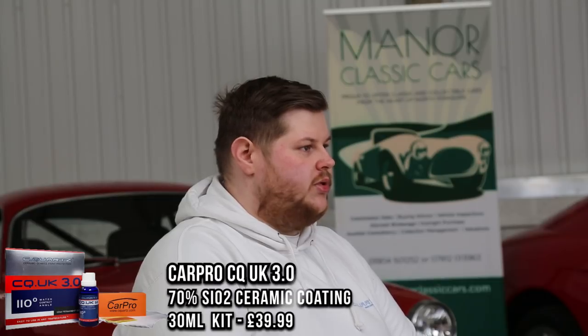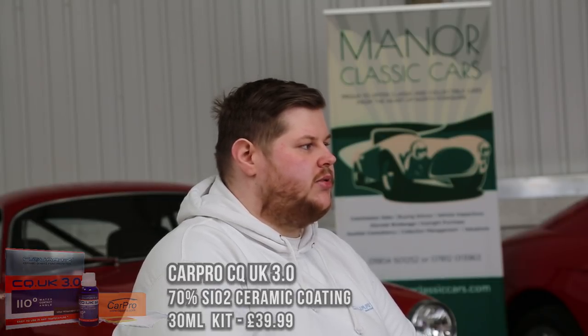Yeah, so most coatings, as soon as they're dry, they can go back to the customer. Certain coatings like our C.Quartz UK, we recommend reload to be put on top while it's curing, and that just protects it from water spotting and chemicals, because C.Quartz UK is going to take about 4 days. So our approved coatings, the C.Quartz Professional and C.Quartz Finish Reserve, they're going to become chemical resistant within 24 hours. So with them, you would bake it with the infrared lamp, it's going to dry it, it's then going to sit inside overnight, and that's going to give it 12 to 18 hours, and by that point it's almost perfectly cured. And then the customer's taken away a cured coating anyway.